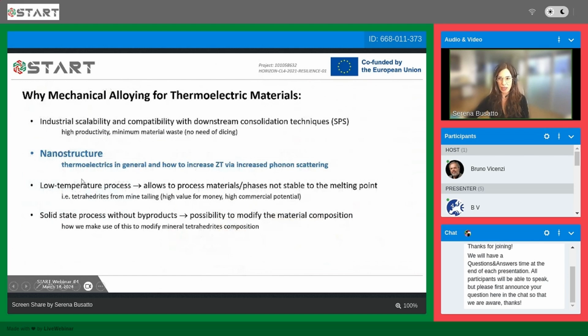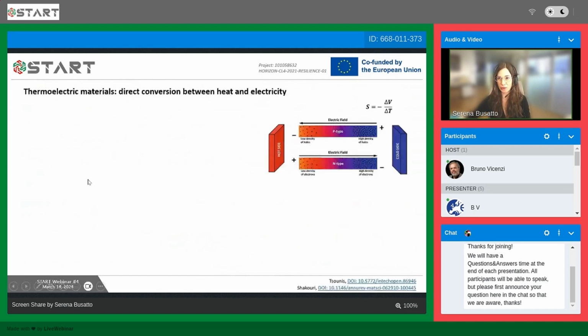Let's go then now to the nanostructure and why this is important. And I will first show you the figure of merit of thermoelectrics, how thermoelectric works. So here is an example of a thermoelectric junction. And what happens in thermoelectrics is that the carriers that are electrons in N-type materials and holes in P-type drift from the hot surface to the cold surface, and this builds an electrical potential across the material, which eventually counterbalances the drift. And the proportionality constant of the created potential over the temperature gradient is called the Seebeck coefficient, and describes the thermal power of the material.